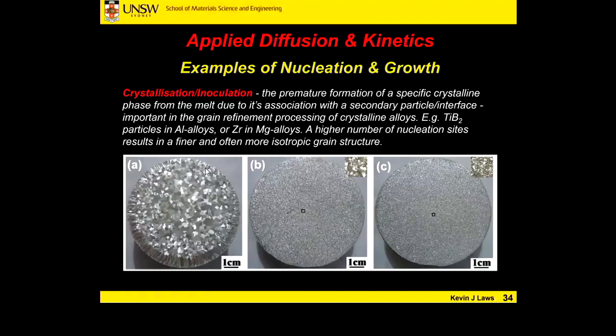Why are they there? Two reasons. They're probably being inoculated from the surface of our vessel we've cast our sample into, plus the edge of the vessel is going to be cooler, so grains will grow inwards to the centre. But then we've essentially got these equiax grains in the centre. Some of them have slight dendritic structures, but they're generally an equiax grain. So they're nucleated in almost a homogeneous way, away from the outer skin of our casting as it's cooling.